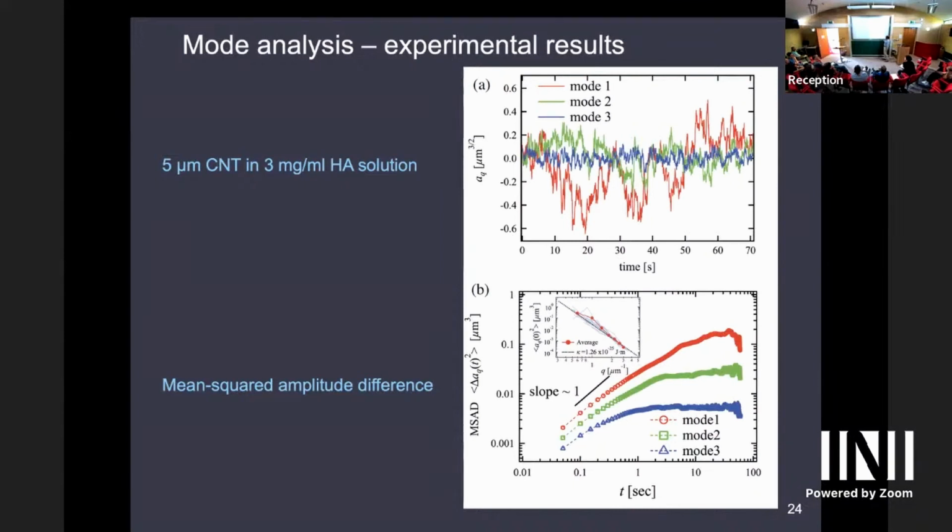Okay, so also you want to check on the spectrum of these mode amplitudes, and you expect something like a q to the -4 slope here, which I didn't put the slope here, but it should be q to the -4. You can see here, lots of magnitude here, and it's pretty close. So that's within the noise range. So that seems to work fine in this equilibrium system, and gives us a stealth probe, and gives us that sort of multi-wavelength, multi-length scale microrheology probe.